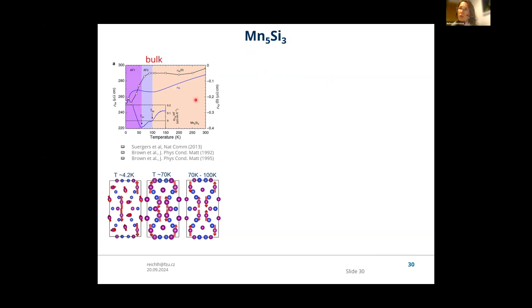From the paramagnetic state it goes to the collinear phase, where the spins are arranged collinearly, and in the low temperature phase the spins get some non-collinear ordering, and at very low temperature even more manganese atoms get ordered, and it's getting really complicated. So for us, the medium temperature phase, the collinear phase, is the interesting one, and we try to grow it in the form of thin films.